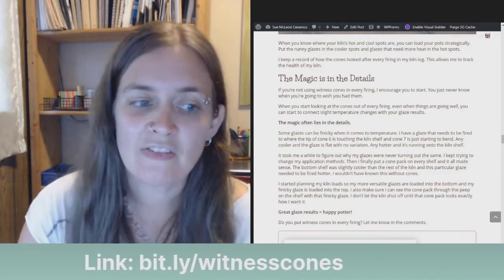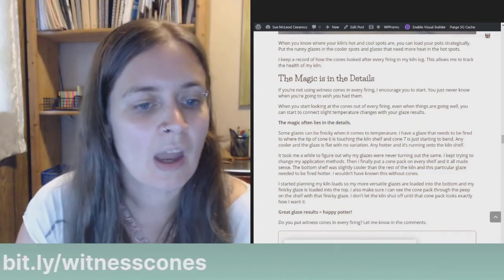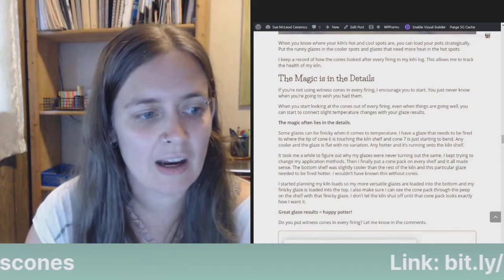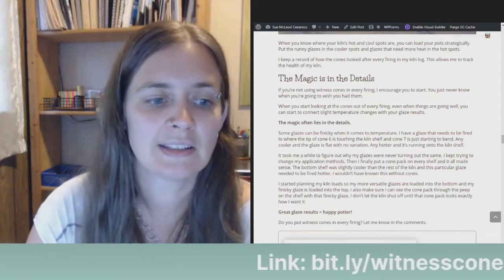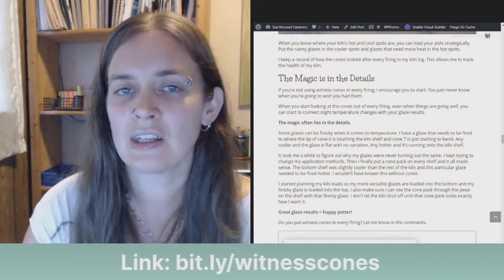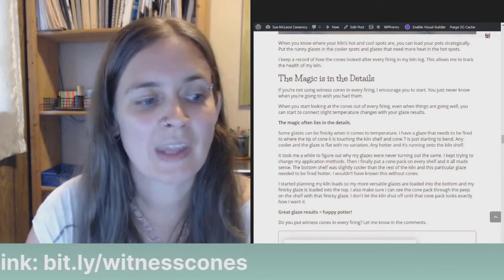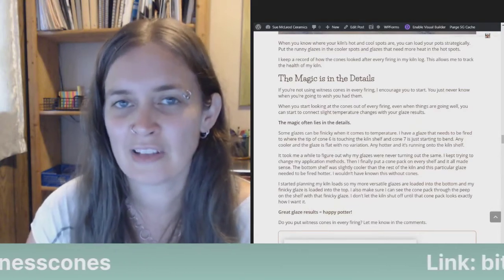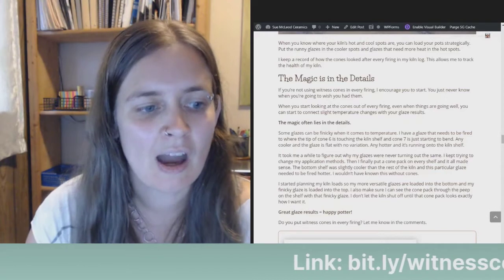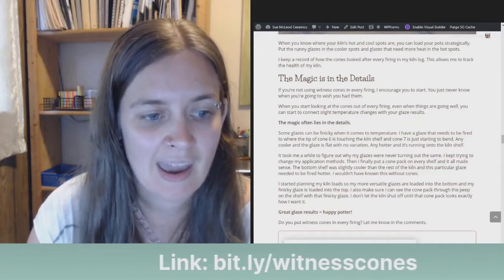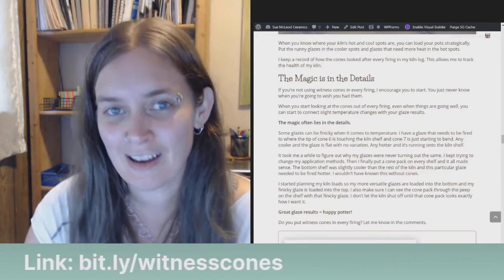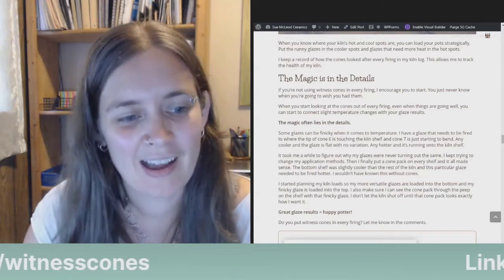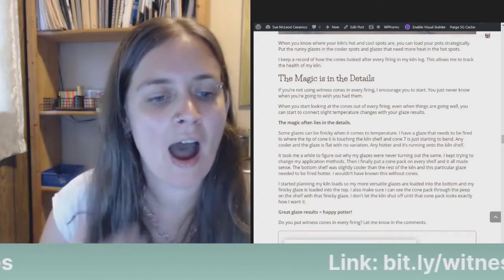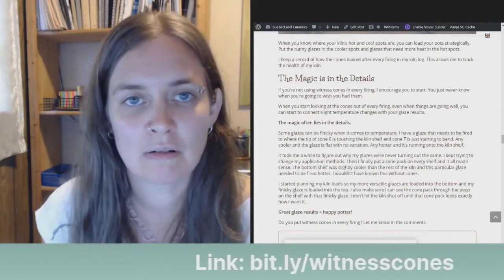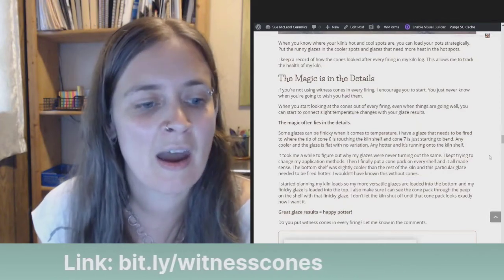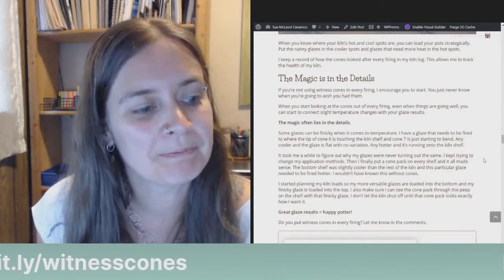Some glazes can be finicky when it comes to temperature. I have a glaze that needs to be fired to where the tip of cone 6 is touching the kiln shelf and cone 7 is just starting to bend. Any cooler and the glaze is flat with no variation. It's just not very exciting. And any hotter and it's running onto the kiln shelf. So it's a very troublesome glaze, but I learned how to fire it strategically by using witness cones.